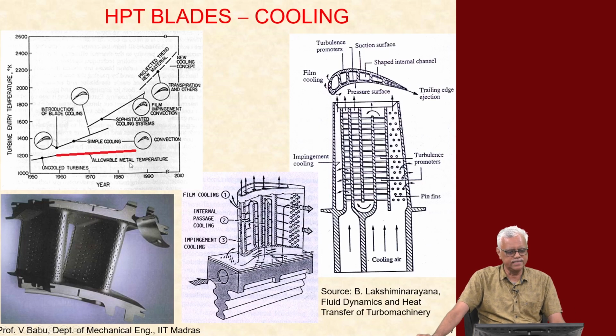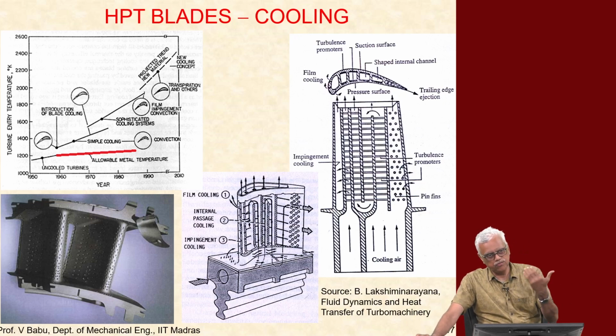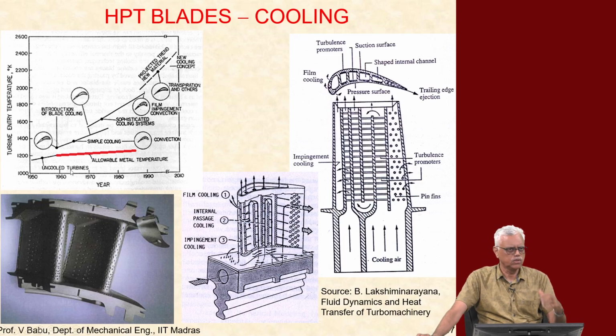If you look at the turbine entry temperature, over the years it has been going up like this, whereas the allowable metal temperature has stayed more or less at about 900 degrees Celsius or so, but the operating temperature continues to increase, because the higher the operating temperature, the higher the efficiency, basic thermodynamics. The gases that flow over the blade are at such high temperature, but the blade metal itself must be maintained at temperatures about 400 degrees Celsius less. So, many things are done.